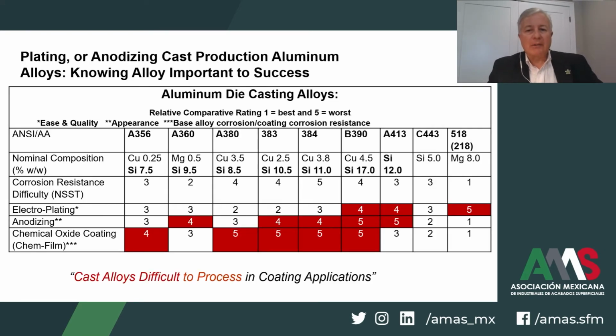These are the more common cast alloys that we see for surface finishing requirements. This represents a small portion, but the point here is that not all cast alloys are alike, and the method of casting, as well as the alloy and the resulting orientation of silicon within the alloy, will impact the success or the failure for any coating application. As you can see, the higher the silicon in the alloy, the more difficult rating is shown to process, not only for anodizing, but we include plating and also chemical conversion coatings, which is not commonly attempted for castings because of the poor results with corrosion performance.